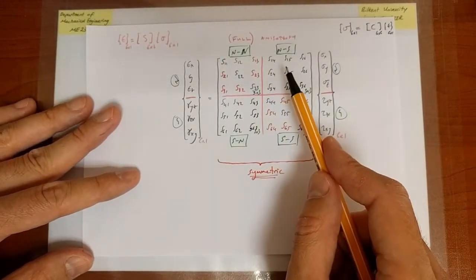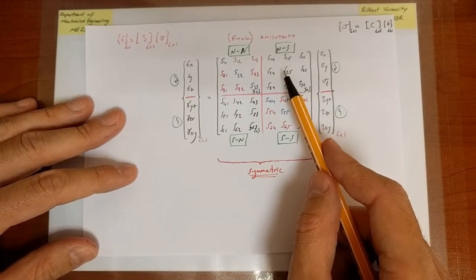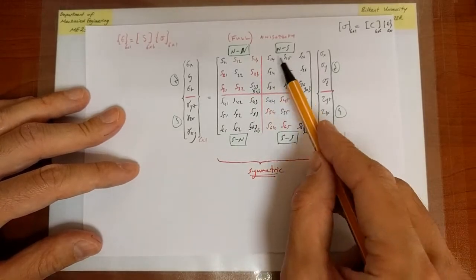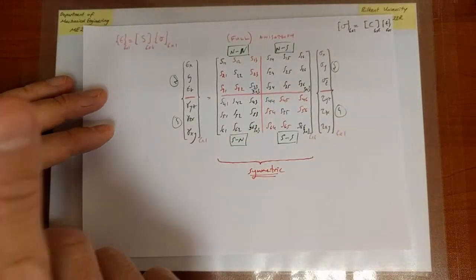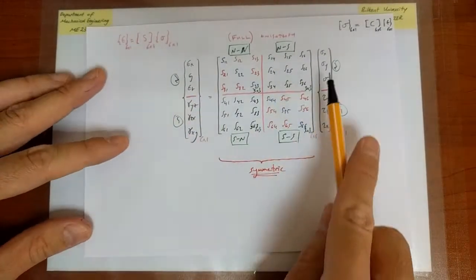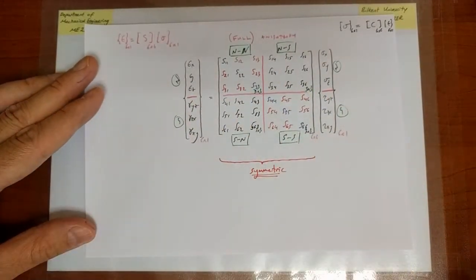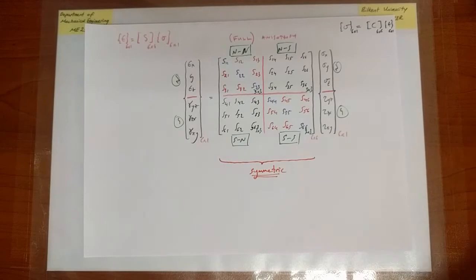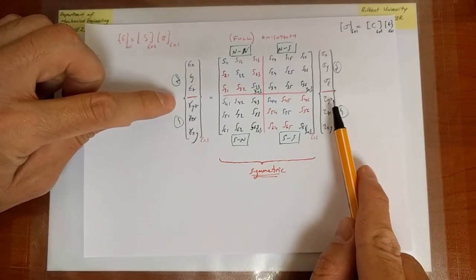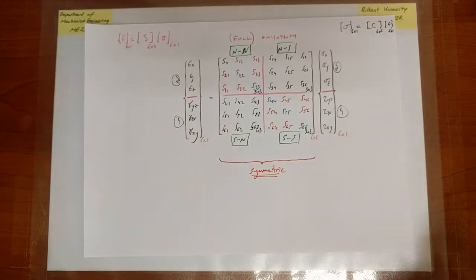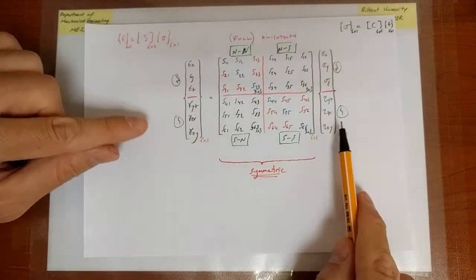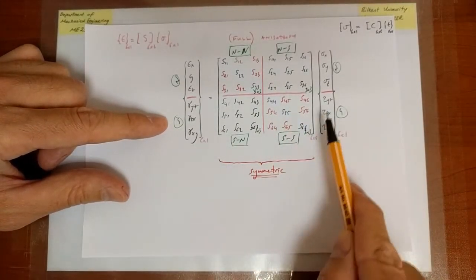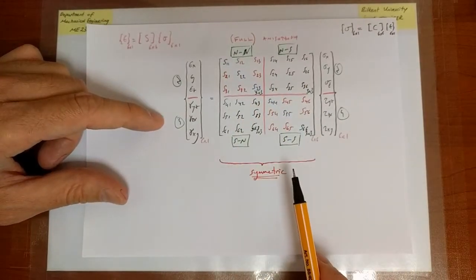You would know that there's some information that's missing. If I give you just E and nu, I have to also tell you that the material is isotropic, so you figure out that these are 0, etc. So the hint of isotropy tells you a lot about the structure of this matrix. So now if I don't give you that information, and I tell you, okay, the material is anisotropic, so I want you to work with it, I give you a stress, you need to give me what the strain is. The question is, how many constants should you ask for to be able to do that calculation? In other words, how many values do I need to supply to you so that you can know the full form of the compliance matrix?